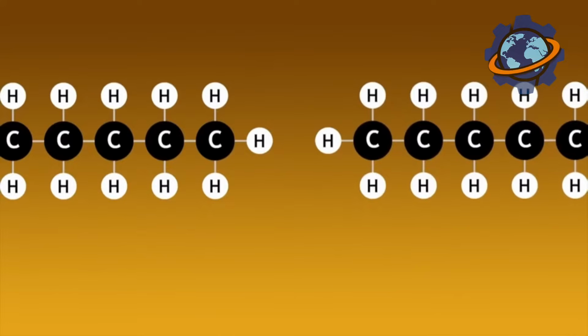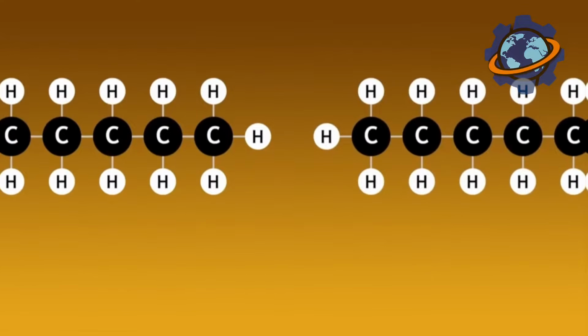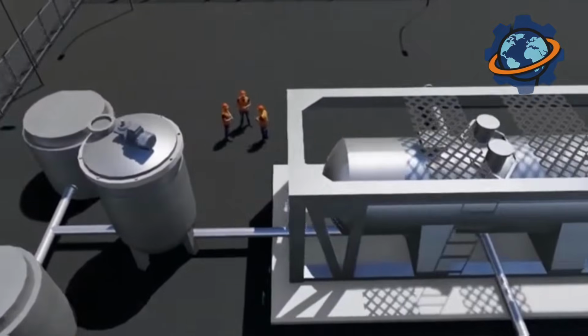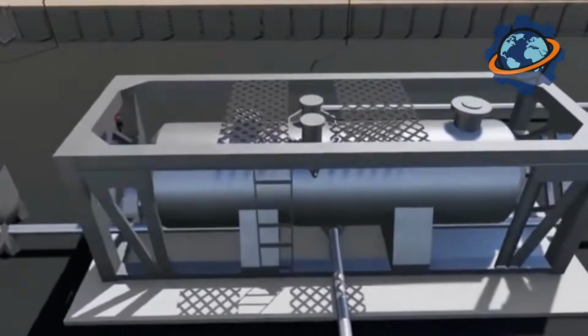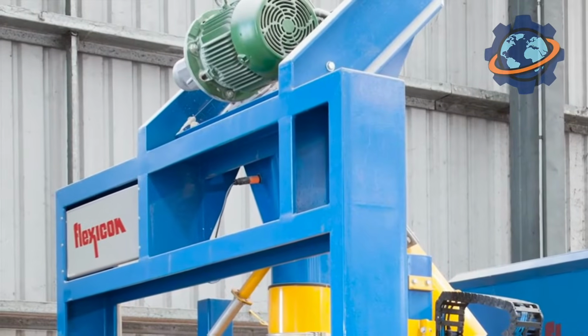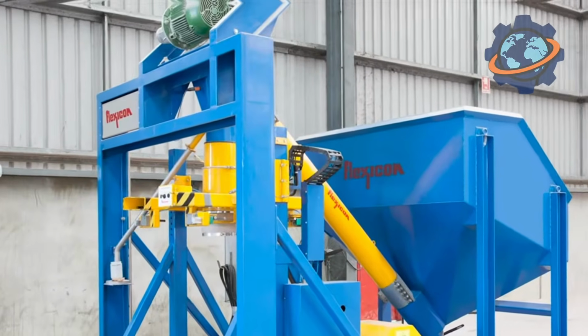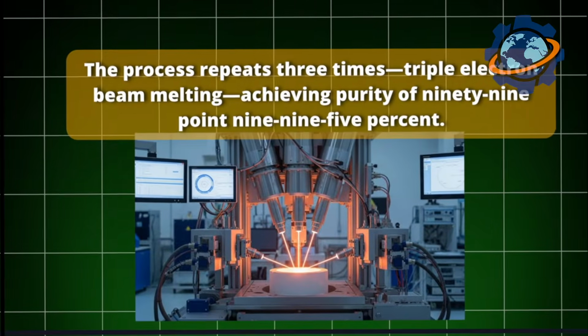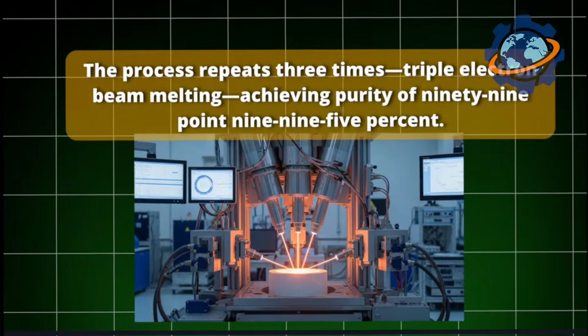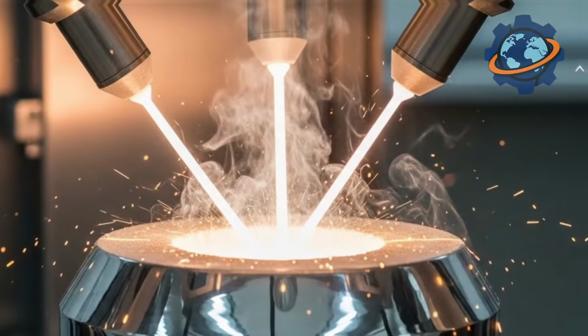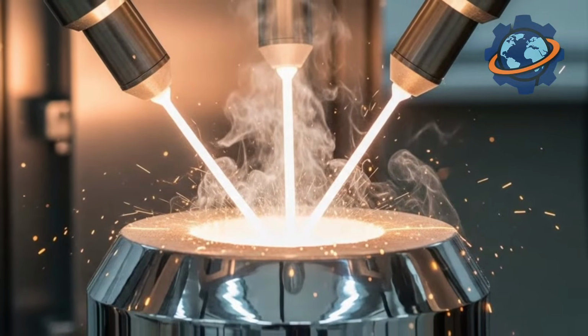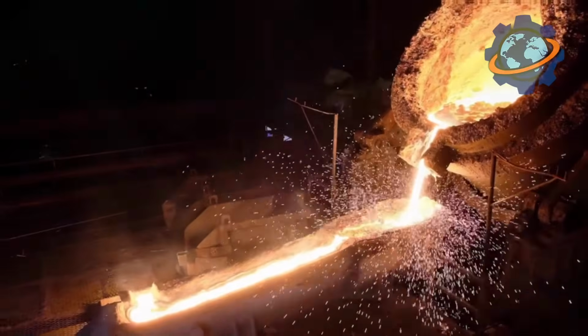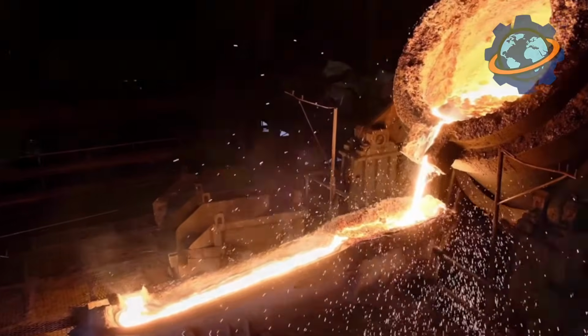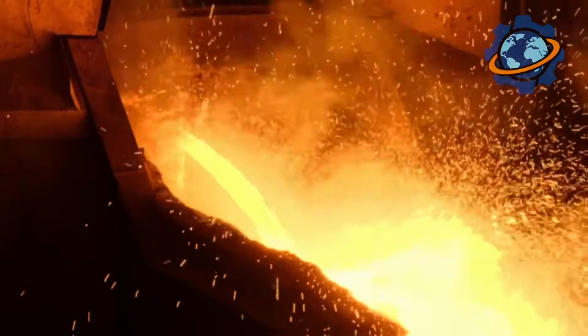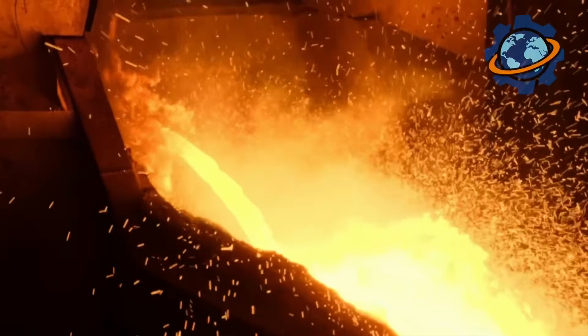Molten droplets fall into a water-cooled copper mold, solidifying as an ingot. Impurities vaporize in the vacuum: magnesium, iron, carbon, everything except zirconium boils away. The process repeats 3 times, triple electron beam melting, achieving purity of 99.995%. For nuclear applications, this isn't perfectionism, it's survival. Impurities in cladding absorb neutrons, poisoning the reactor, reducing efficiency, potentially causing fuel failure.